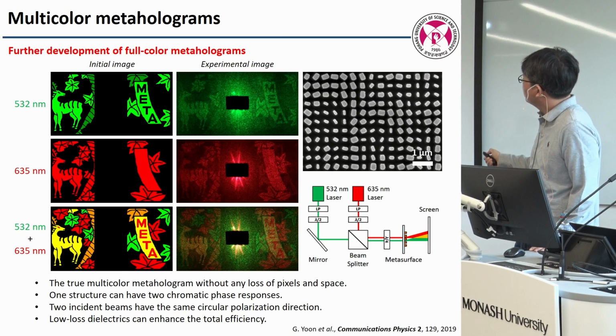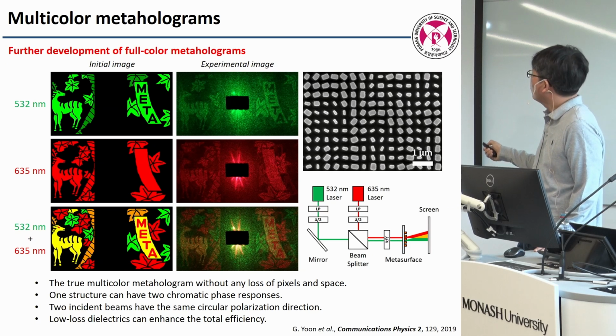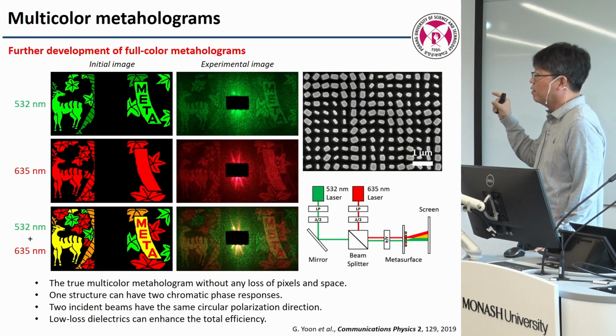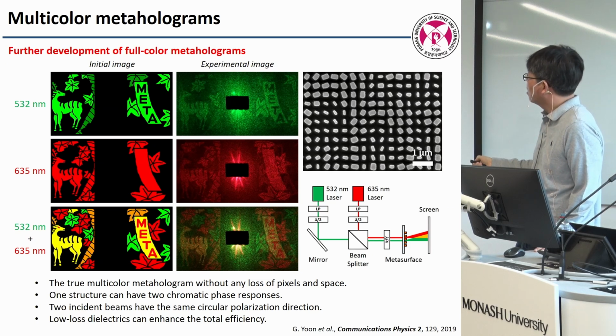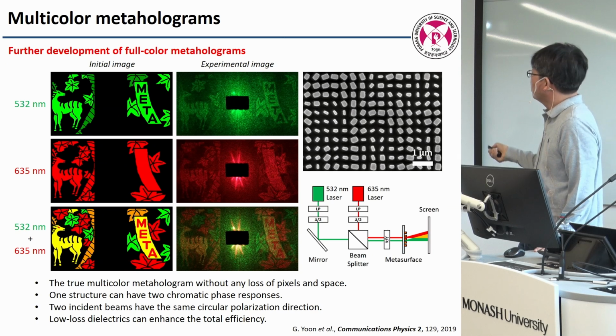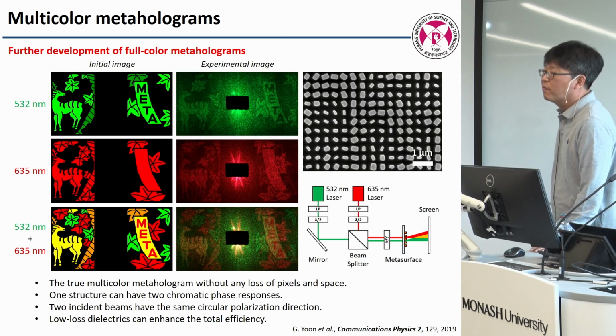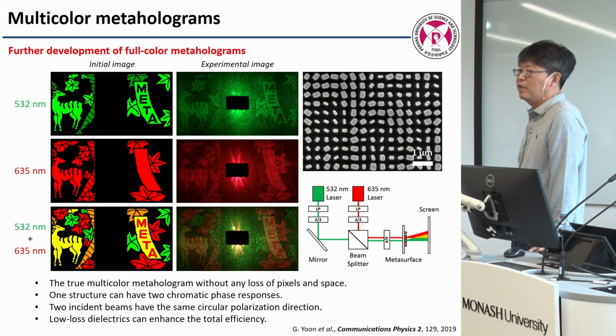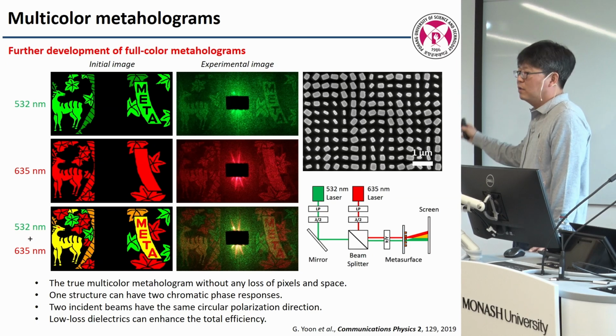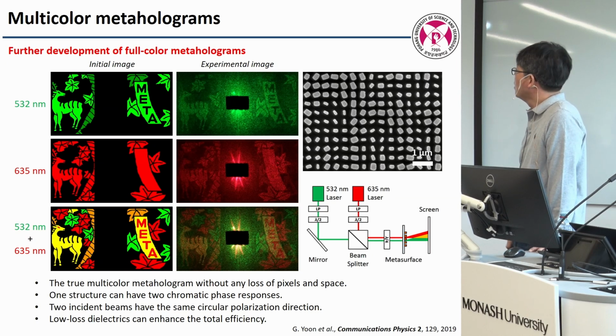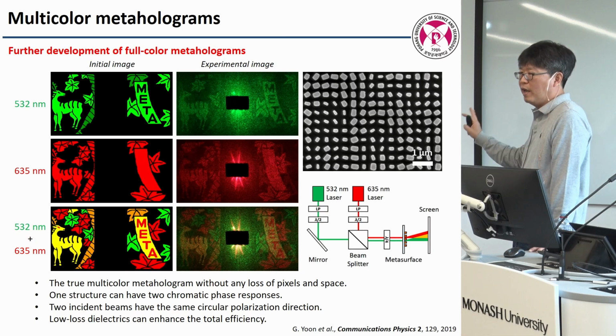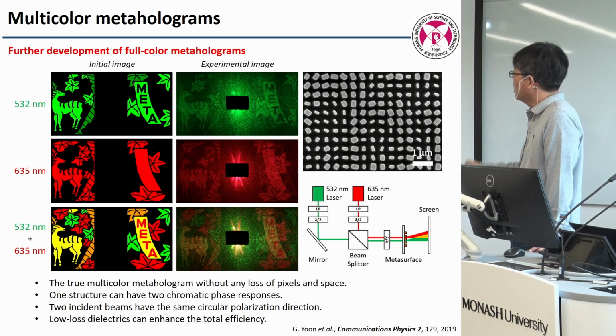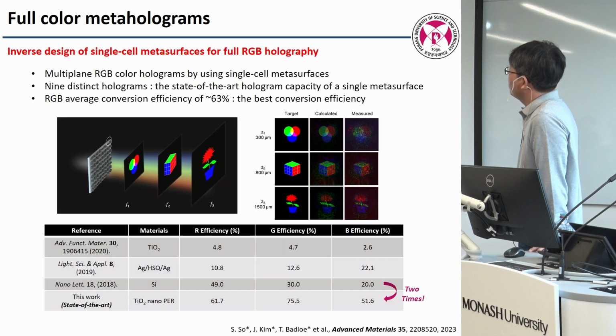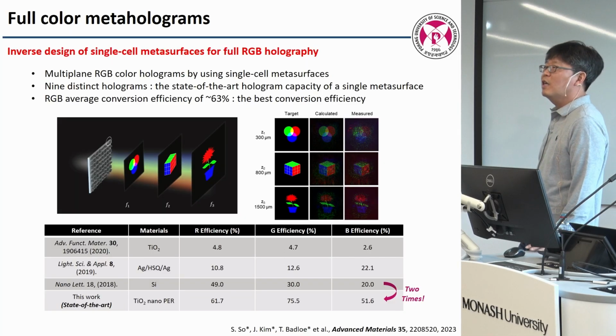So now the unit cell becomes a little more complex. While the rotation happens, their thickness and size also change. So a little more complex, two-color combination. But three colors we failed. This is too difficult. So an analytic solution is not coming out, and this optimization doesn't work because we failed to generate the three colors by using this method. But we didn't give up.